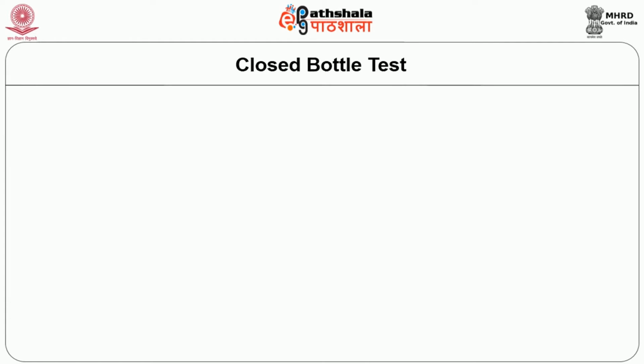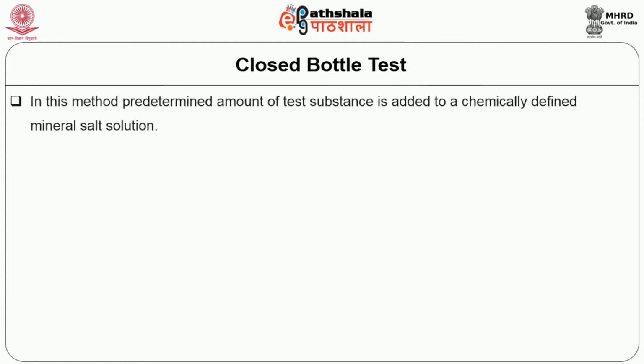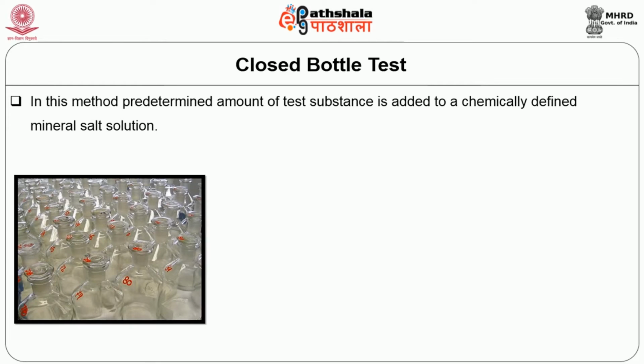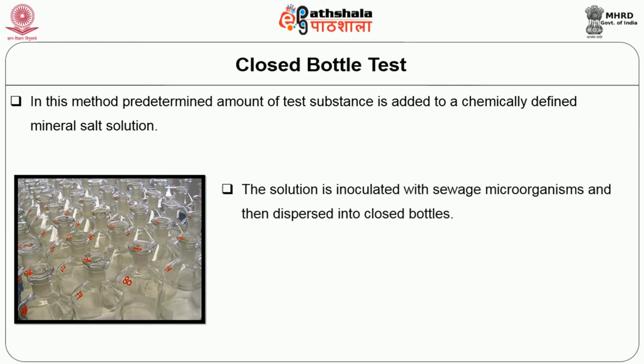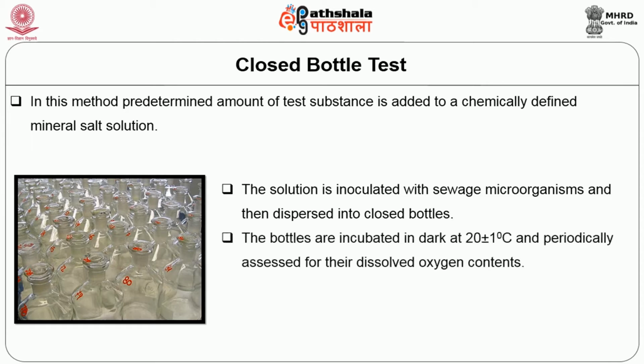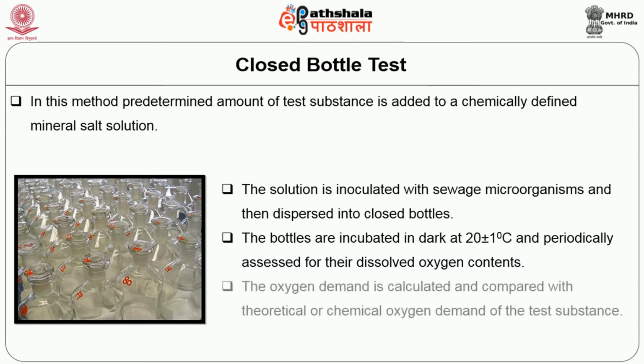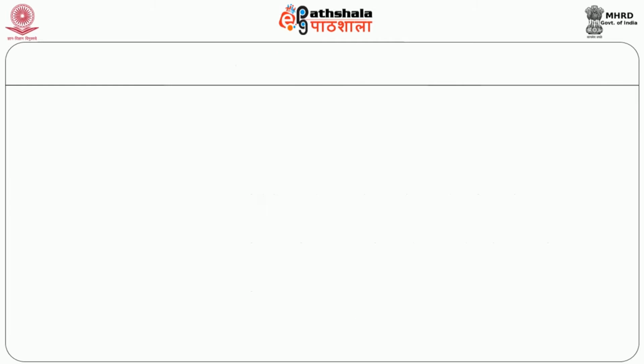Now the second method for degradation assessment is the closed bottle test. In this method, a predetermined amount of test substance is added to a chemically defined mineral salt solution. The solution is then inoculated with sewage microorganisms and dispersed into closed bottles. The bottles are incubated in dark conditions at a temperature of 20 plus or minus 1 degree centigrade and periodically assessed for their dissolved oxygen content. The oxygen demand is calculated and compared with the theoretical or chemical oxygen demand of the test substance.